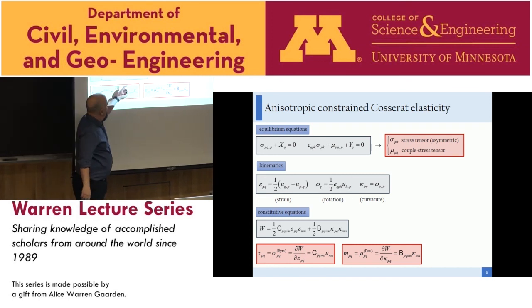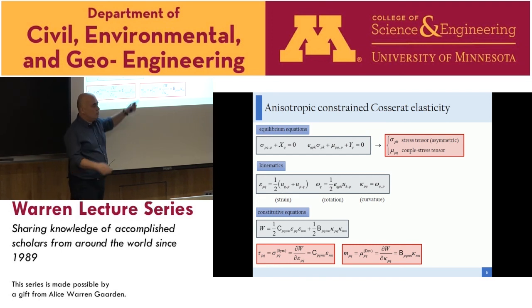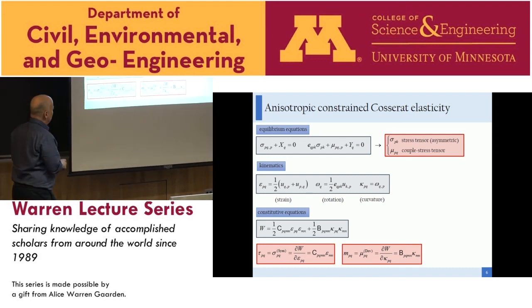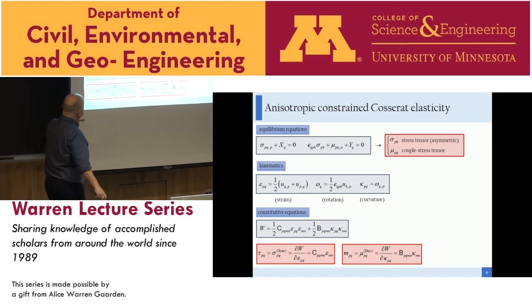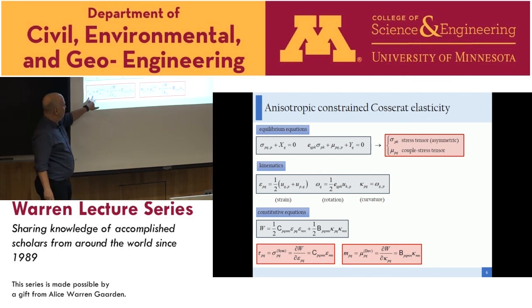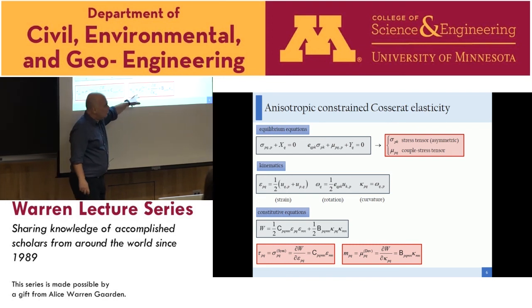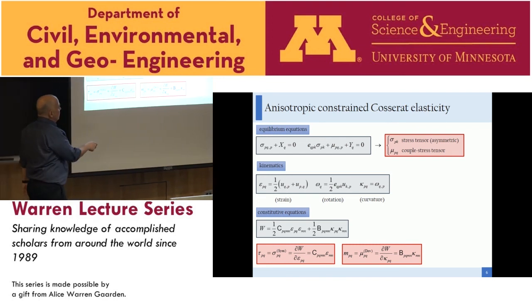We could have a mixed term coupling strain and curvature, but we wanted to keep things simple. From this strain energy we derive the symmetric part of the stress as the gradient of the strain energy with respect to strain, and the deviatoric part of the couple stress tensor as the gradient with respect to curvature. This is the constitutive framework we use.